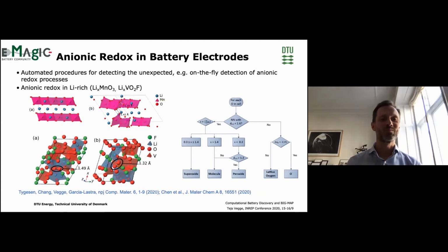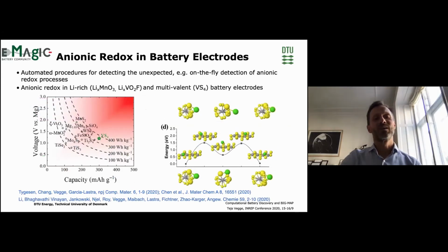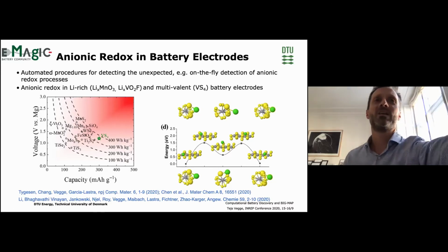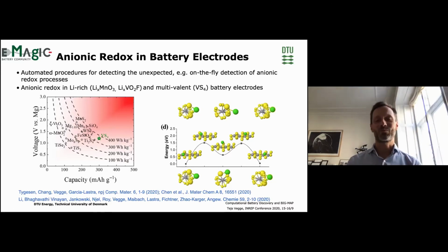To get back to the magnesium ion system, we've also seen that we can analyze potentially interesting electrode materials like vanadium sulfide that we heard about earlier today, which has a high capacity. What is interesting, and this is work done in collaboration with colleagues at KIT and Piotr Jankowski from our group, is that also here in vanadium sulfide, we actually see anionic redox processes taking place. So we see the transition of S2 2- to S 2- species in the system contributing to the capacity. So what we're seeing here is really that we need to be able to assess the unexpected.